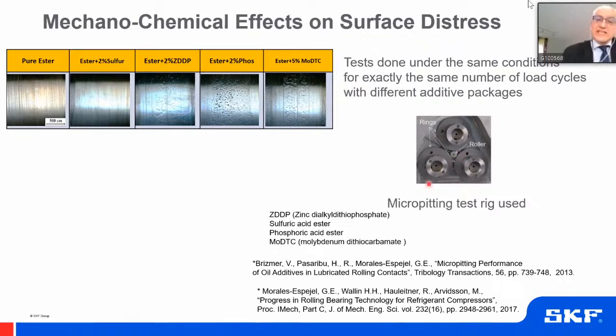So if you run an experiment exactly with the same operating conditions, the same roughness, and even the same oil, but just changing the additive composition, the description is here, then you can expect very different behavior for the same conditions. And that is precisely because the additives will modify locally the friction coefficient and the wear coefficient. And that has consequences in the stresses that we have in the surface.